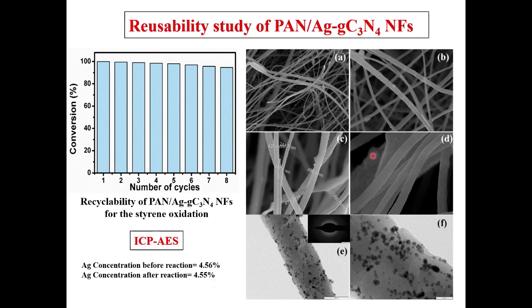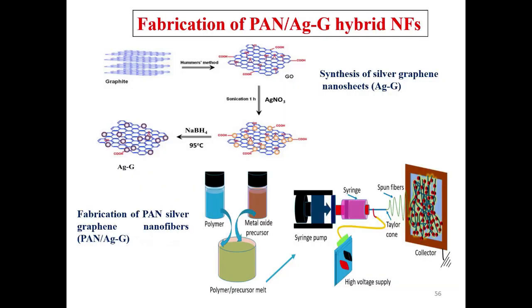And we have done the morphology, there is no change in the structure of the PAN/Ag-g-C3N4 nanofiber at all, only small disturbance, small leaching out of the silver particles from the surface. Other than that, the material is as such, and we can even use it further, only a nominal decrease in the percentage of the product being observed.